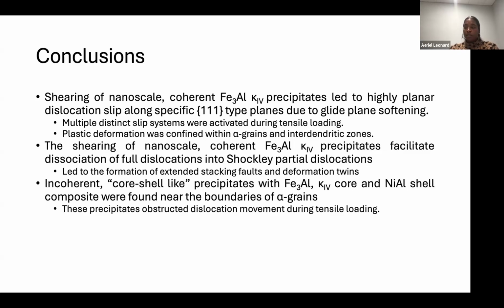They facilitate planar slip. They allow hardening to happen in the material. So it's really getting the balance between the ductility and strength that we're always trying to achieve. And what we think is that this stair-rod cross-slip mechanism is really facilitating the formation of these extended stacking faults and deformation twins in the material, and that we do have these incoherent core-shell-like precipitates with an iron-aluminum core and nickel-aluminum around the boundaries that also obstruct dislocation motion at the interface.